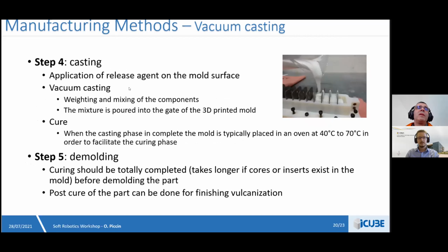So you have to mix the elements, apply some release agent on the mold surface to ease the extraction of the part, and then the cure of the part is completed when you place the part on the mold in the oven. So the curing phase is activated by heat.